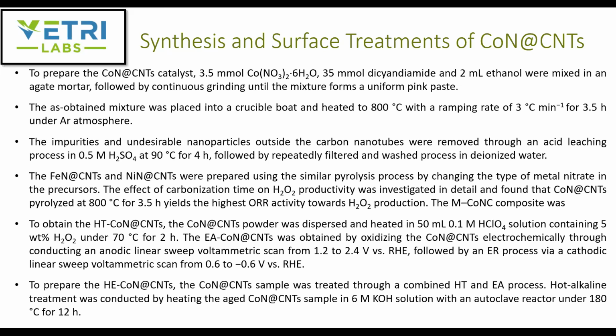And they combined these two, the peroxide treatment and electrochemical activation, and called it HE cobalt nitrogen doped carbon nanotubes. Basically, combining both processes, first doing the peroxide treatment and then using that as an initiator to do the electrochemical activation. And they also did a hot alkaline treatment of this HE cobalt nitrogen doped carbon nanotubes in 6 molar KOH solution in an autoclave reactor at 180 C for 12 hours to see how the other functional groups would do. When they do this alkaline treatment, they get hydroxyl groups, and they compared how that would compare to the presence of hydroxyl and epoxy groups.